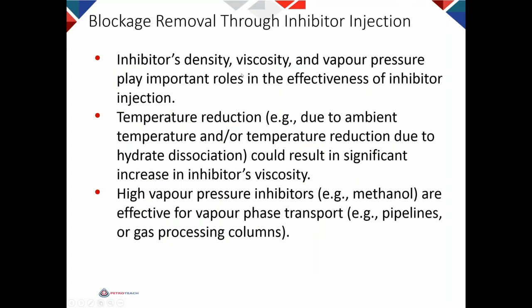Obviously, there are many factors affecting the choice of inhibitor: viscosity, density, vapor pressure. They all play a major role in the effectiveness of the inhibitor. When you have inhibitor, the dissociation of hydrate makes the system cool. As the system becomes cold, then the viscosity will increase.